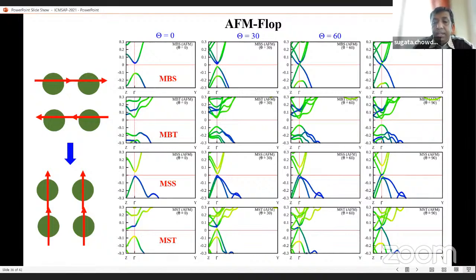On the other hand, the most important thing we found out is that the manganese antimony selenide structure's ground state is antiferromagnetic and it is a trivial insulator. But when we apply the magnetic field, it is a non-trivial insulator. So there is a trivial to non-trivial phase transition happening for the manganese bismuth selenide and manganese antimony selenide structures.